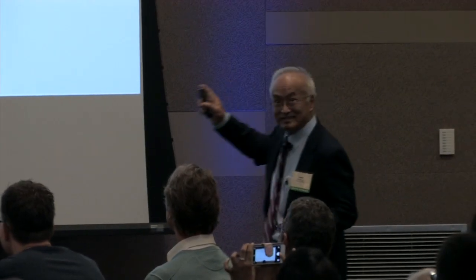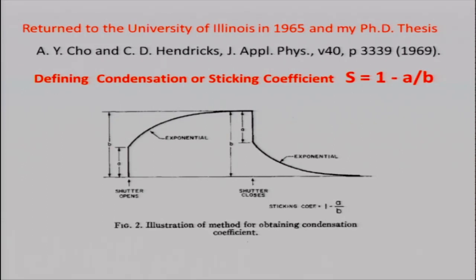So in the thesis I finally wrote, I of course had an advantage. I was doing surface physics work at TRW, and I just extended that as my thesis. In my thesis, I defined the condensation or sticking coefficient as S. S is equal to 1 minus A over B. A is the abrupt change when you open the shutter, and then the exponential goes to the equilibrium value of B.